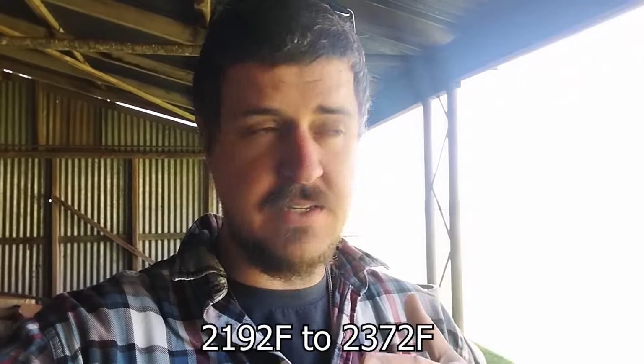All right, so we've got it in the forge, and it's heating up. We want to try and bring it right up to that 1200, 1300 degrees Celsius range using the infrared thermometer. You'll recognize it as just forge welding temperatures, but it will look different on a bloom to what it would look like with, say, carbon steel. On a bloom, forge welding temperatures look like bright orange, whereas on carbon steel it looks like a yellow in most ambient environments. So you'll learn pretty quickly, and if you have a thermometer or a thermocouple, you'll be able to actually tell when you're at temperature.